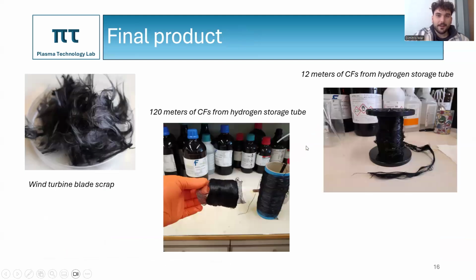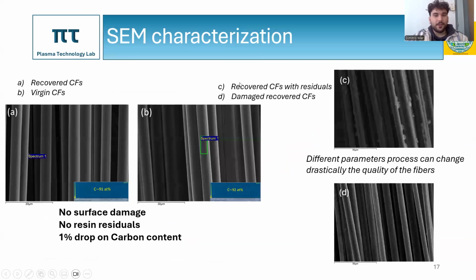Other than that, here are some of our final products. You can see some short fibers that come from the wind turbine blade scrap right here. And also you can see some continuous fibers that come from the hydrogen storage tubes of either 12 meters or 120 meters. And those fibers are really good quality because we did some characterizations on them. First of all, we did some SEM characterization. You can see on figure A the recovered carbon fibers, while on figure B the virgin carbon fibers. You can see that the recovered fibers have no surface damage and no resin residuals on the surface, with only 1% drop on their carbon content.